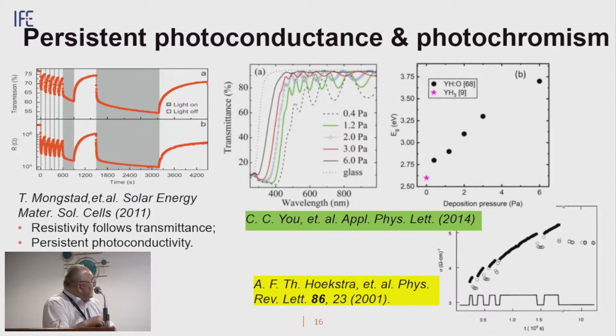Then, when we analyzed the behavior of the transmittance spectra and this electrical conductivity, what we found is that after illumination is off, it relaxes over a very long time. This is what we know from wide band gap materials. It's long-term, or persistent photoconductance. So if it's persistent photoconductance, and it's correlated with optical properties, then we can say it is persistent photochromism. Since it's a new material, we didn't know the mechanism of the photochromic effect. Then my next task was to clarify it.